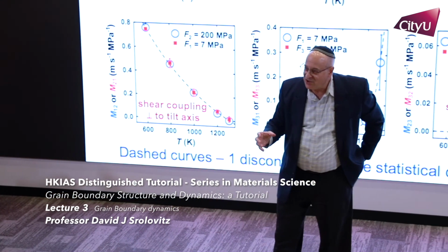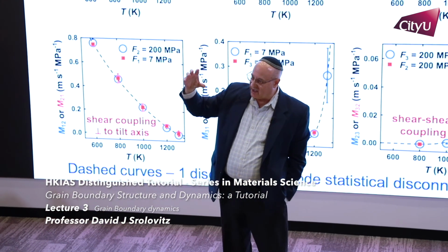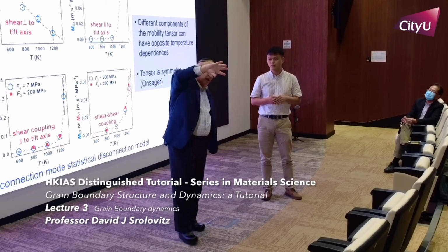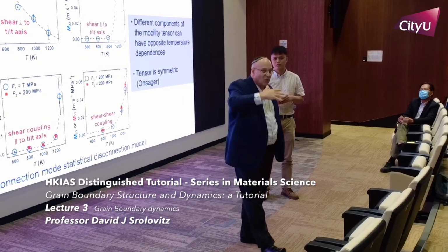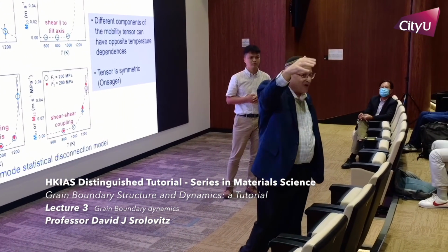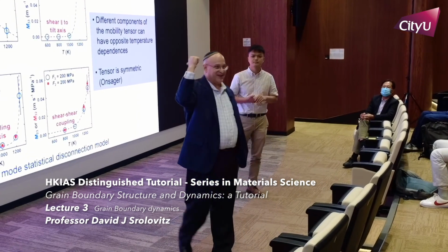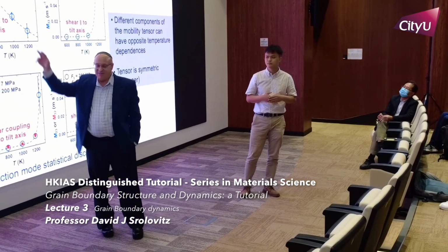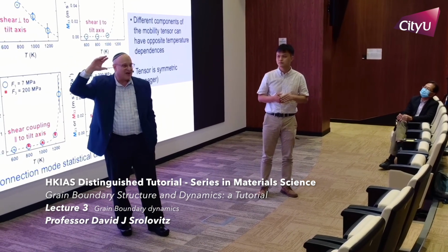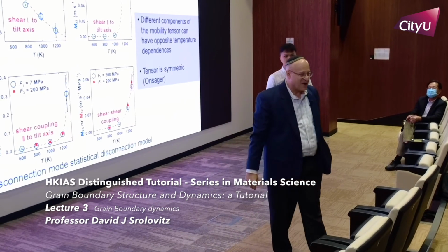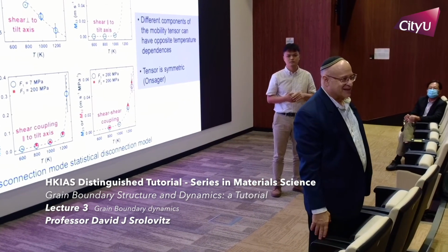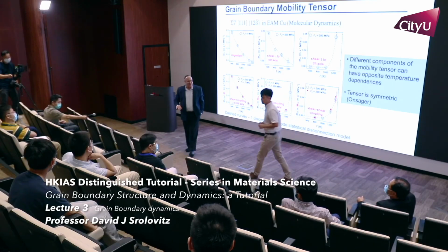But if you actually look at crystallographic texture, it changes during grain growth. And if you watch any individual grain, many grains rotate while the grain boundaries move. All of that is because of this shear coupling. So this may be the biggest term, but there are certain phenomena that you can only understand when you include the richness of how grain boundaries really move, not the sophomore version. Hope there are no sophomores here.